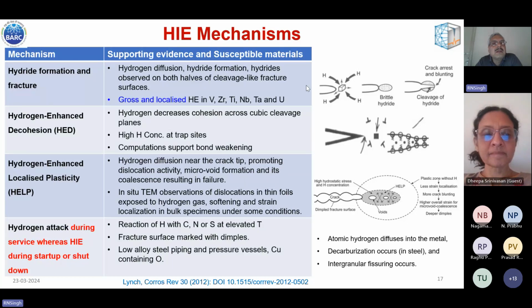So in all metals, one can go for hydrogen concentration analysis. However, in the case of steel, the hydrogen concentration will depend on when the hydrogen loading was done, in what condition it has been stored, and whether hydrogen is present when the actual testing is done. So here some suggestions are there.